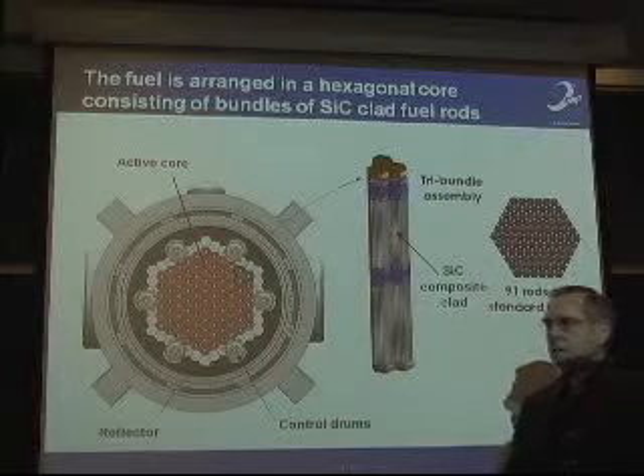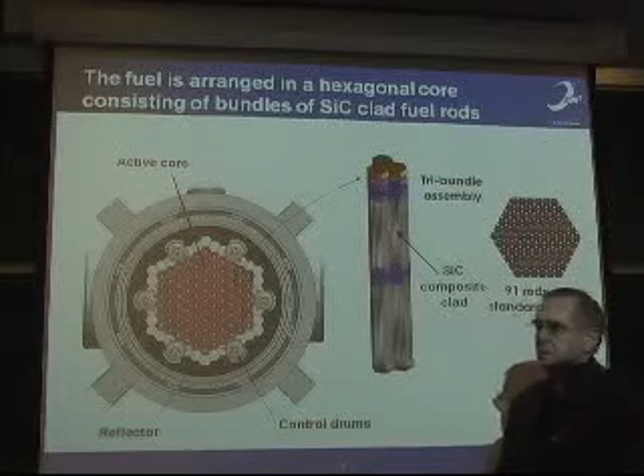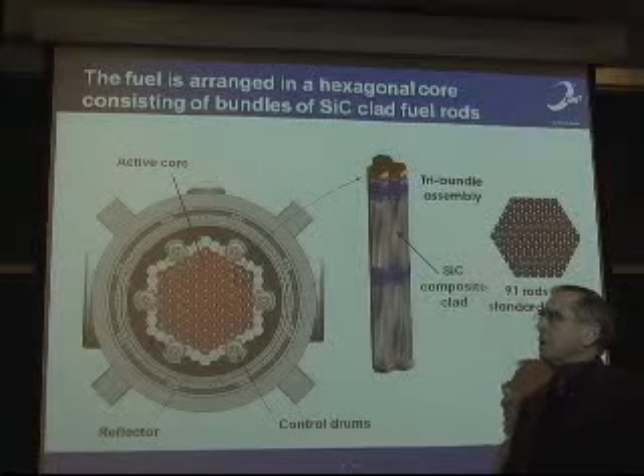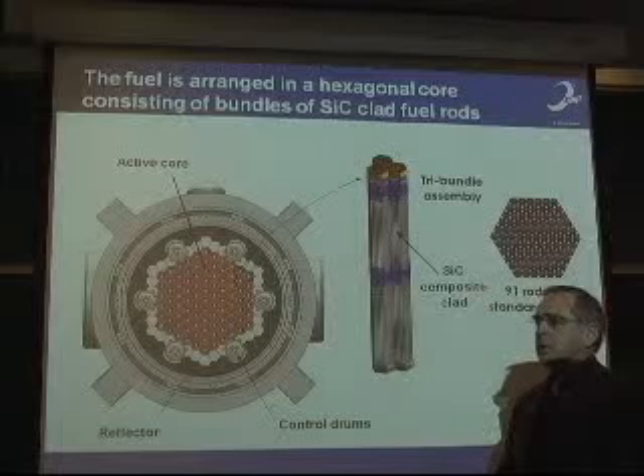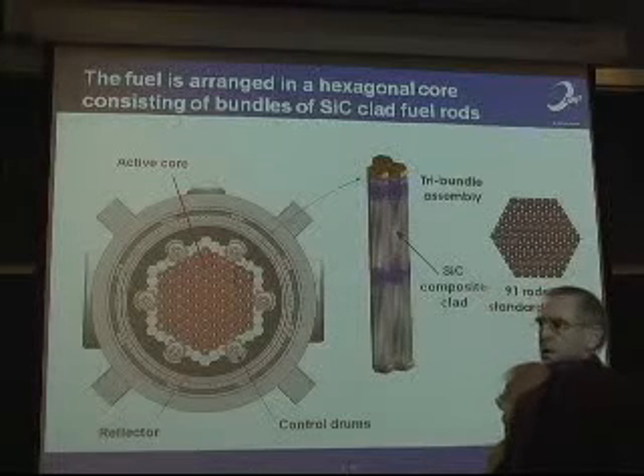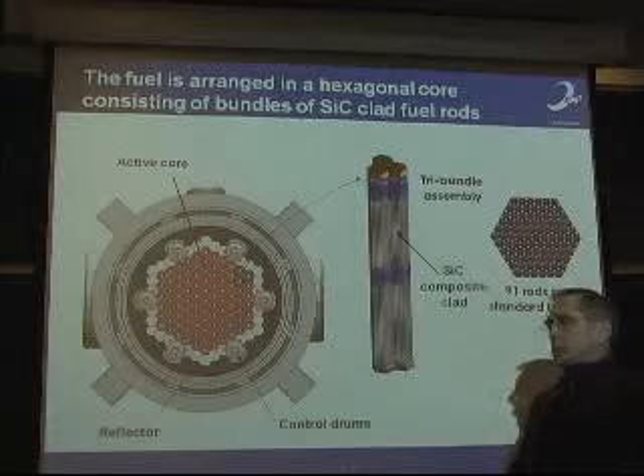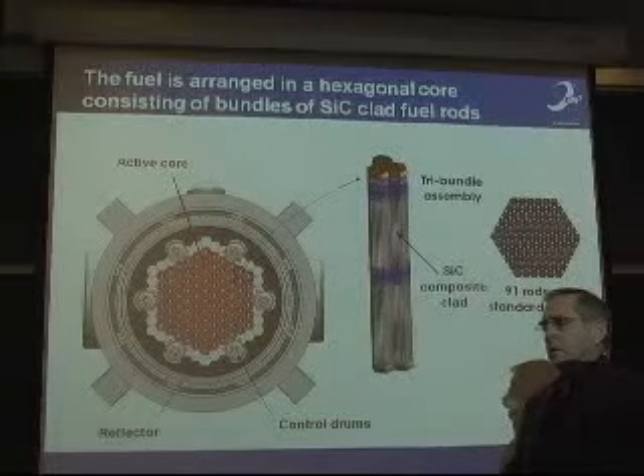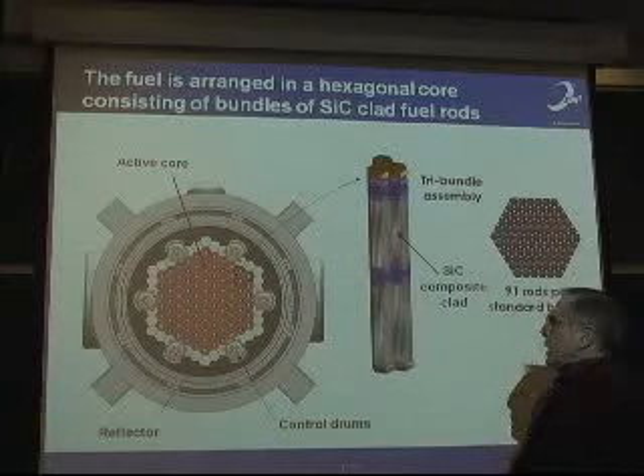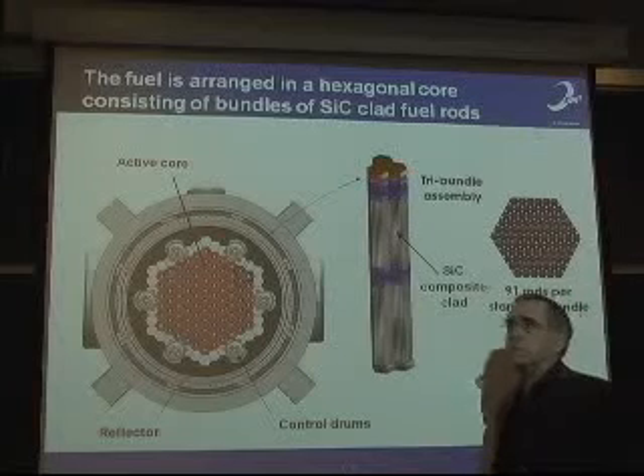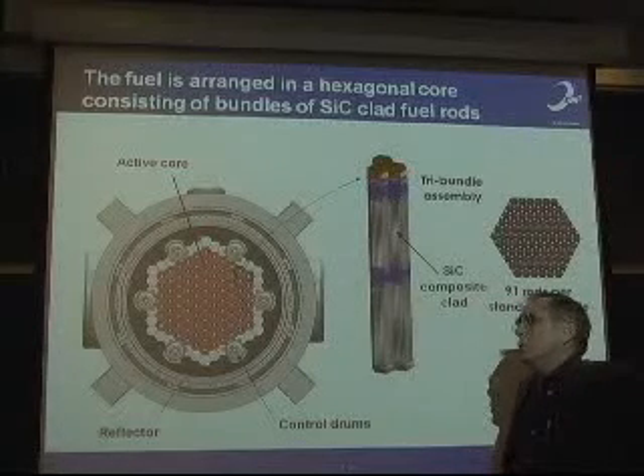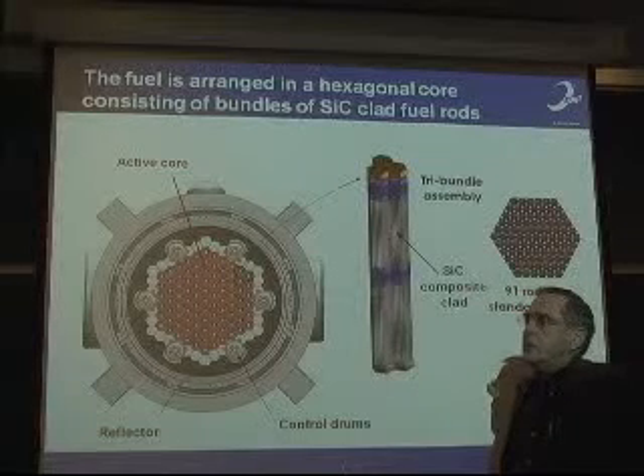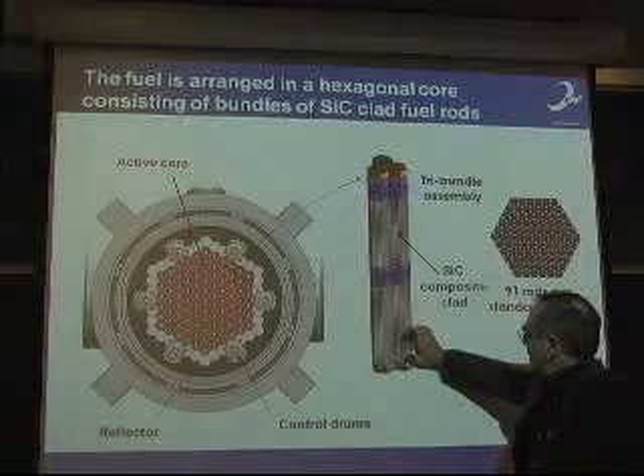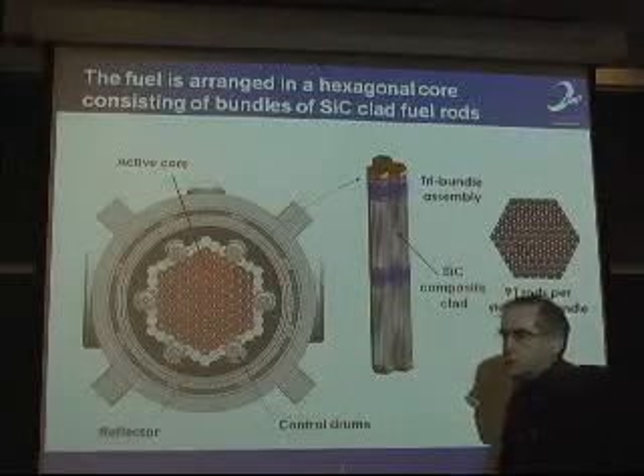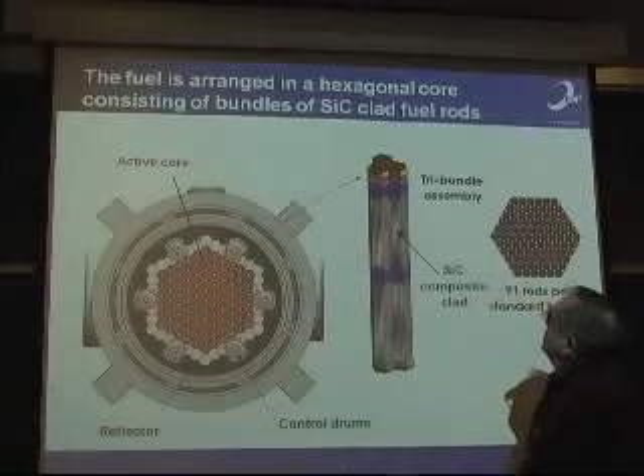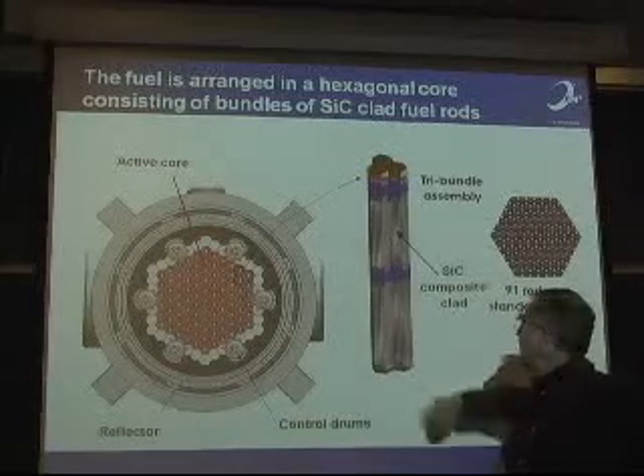What's the diameter of the rods? The rods are 21 millimeters outside diameter. Thickness of the clad is 1 millimeter. So the pellets are about 19 millimeters in diameter. The active rod length is 2.24 meters, and then we have additional length in there. The inner reflector is also in the rods. That's a beryllium carbide. And then there's some additional handling area. So these are close to 3 meters high.